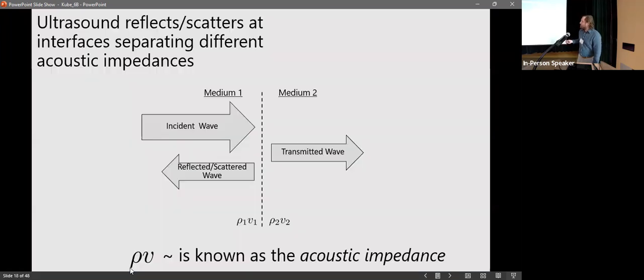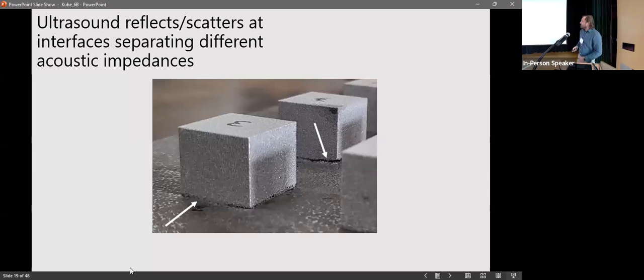So, basic principles behind the technique. We all know that, being acoustics, when you have an incident wave at an interface that separates two media of different density or stiffness, part of that wave is reflected, and part of it is transmitted. In the application, if a crack forms in the part, there's a definite acoustic impedance difference there, so we're going to get a reflection from that. If we have pretty good fusion at the build insert part interface, it might be microstructure that causes that impedance difference that we can sense.